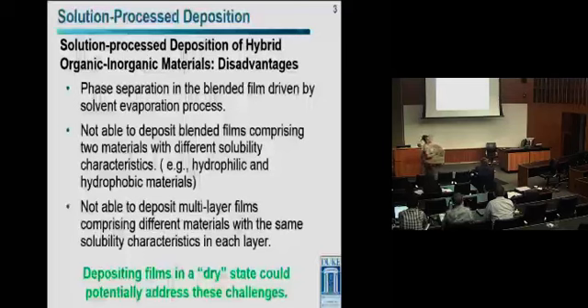And then the third is, again, you're not able to deposit multi-layer films, because an earlier film that you deposited would be destroyed by depositing another layer if it had the same solubility. So there are all these restrictions in terms of what you can make with the solution-based processing. Now, one way to address these challenges is to deposit the films in a dry state. And that's what I'm going to talk about in terms of this MAPLE process.